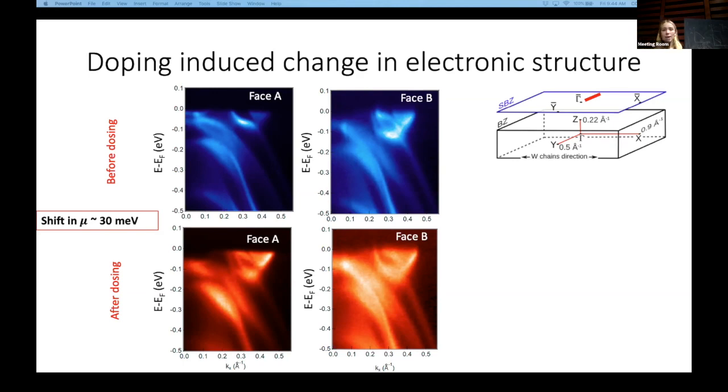So initially, potassium is deposited pretty much all ionized, but as you deposit more and more, it becomes more neutral. So the amount of charge that's contributed is not a linear function of how much time you've been dumping potassium on the surface.